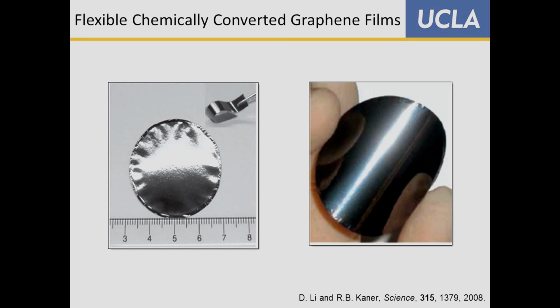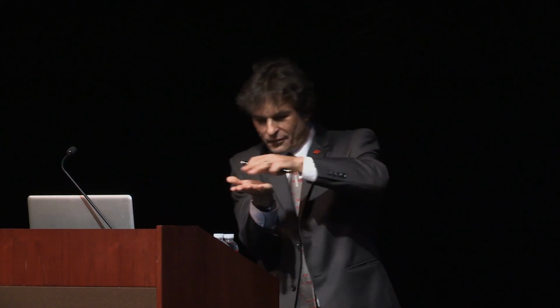So we take this reduced graphite oxide, this chemically produced graphene, and we run it through filter paper, and we just peel it off plastic filter paper. And so this is graphene paper. And it's a little bit different than graphite. Graphite's AB stack. This is just random stacks of many sheets of graphene. And you can see it's very highly reflective.